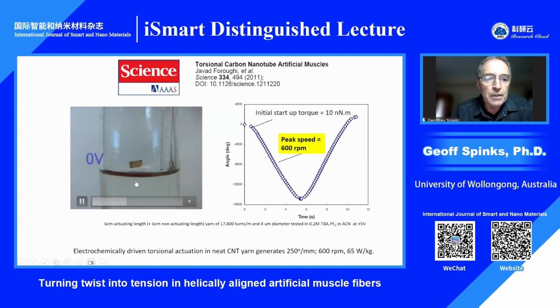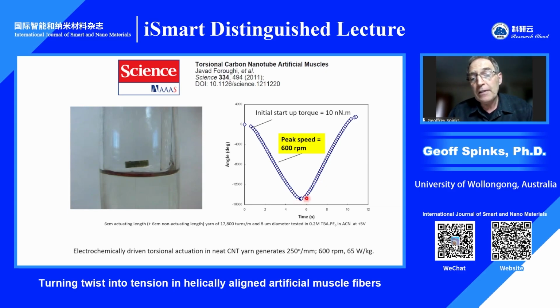So what we're seeing in the test tube in the liquid is a carbon nanotube yarn, which is then suspended in air, clamped at both ends, and it's being electrochemically charged and then discharged, as shown in the video. And what we see, as shown in the chart on the right, is quite large rotations, over 40 full turns of rotation occurring just in a few seconds as the yarn is charged electrochemically, and then that's reversed on discharging completely. The speed was 600 revolutions per minute, and as I mentioned, it's quite a large rotation. It's reversible. We calculated out the power to weight ratio at 65 watts per kilogram, which was quite impressive. And then we published this work as shown in the citation.